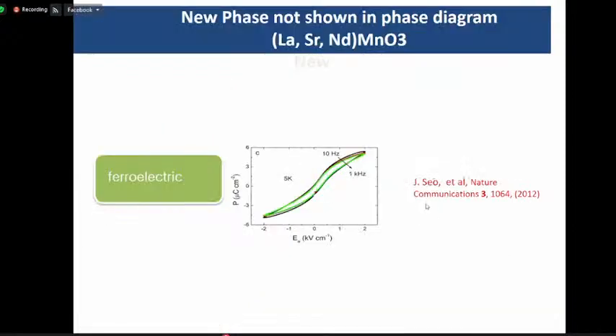Electrically, we found some ferroelectric behavior as well. This is polarization data. This one also shows hysteresis, like magnetic hysteresis. As you will remember, this material is non-magnetic, antiferromagnetic, and insulating. Then they show some ferroelectric behavior as well.